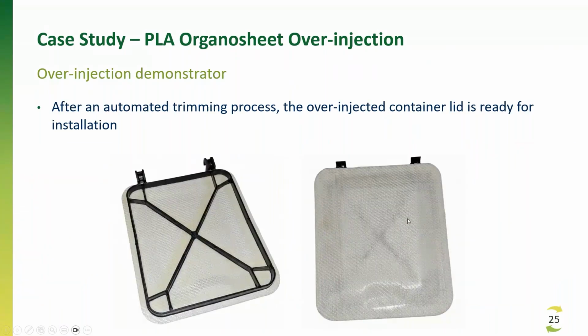As you can see, what I meant by the thin part is that at these points we need to ensure that we have the epoxy. Regarding the temperatures, from our side it was quite easy, because in the case of the polyamide, we over injected with a mold at 90 degrees. So we first activated the epoxy and then put it into the mold, and the process temperatures themselves kept this epoxy activated and allowed us to do the over injection.